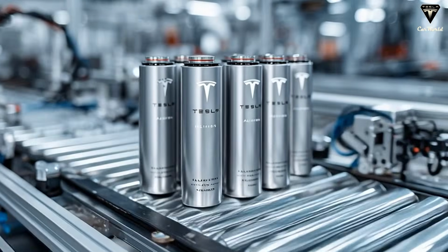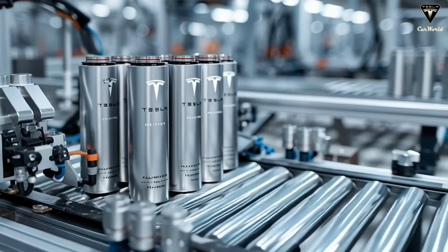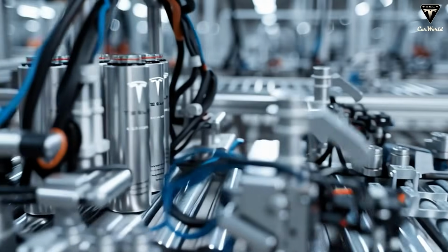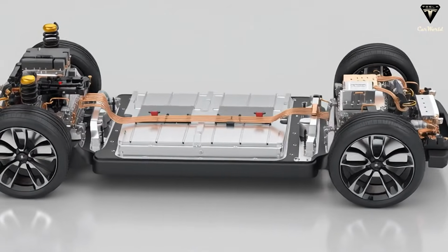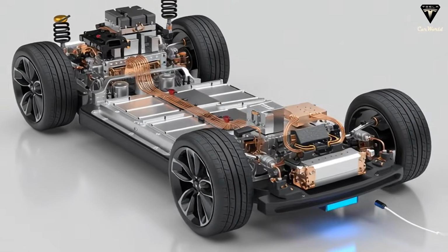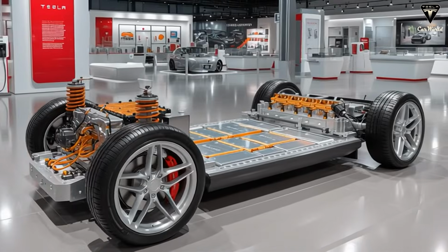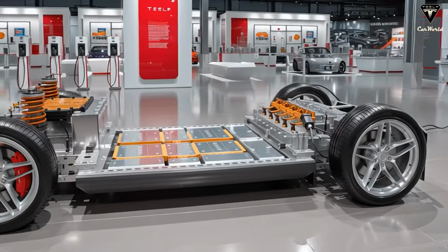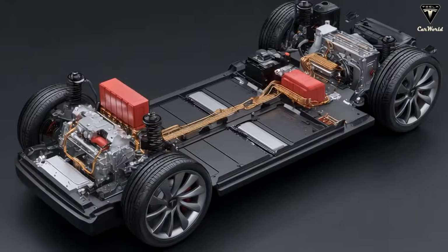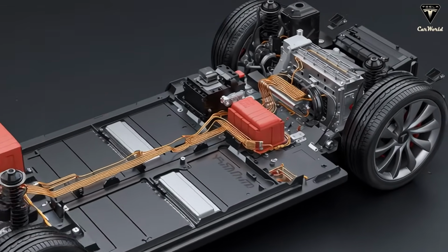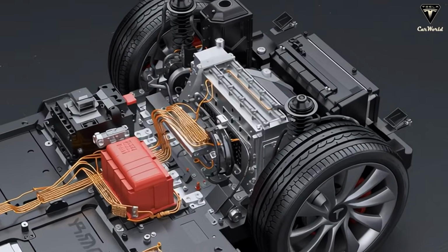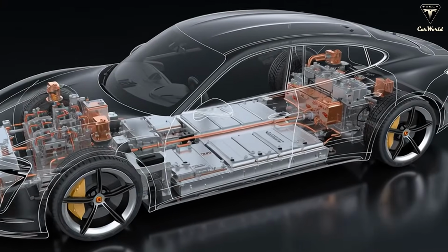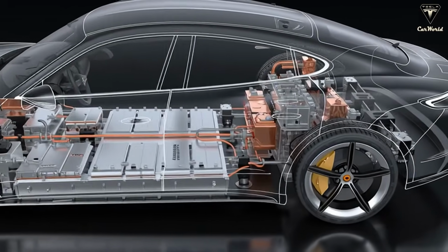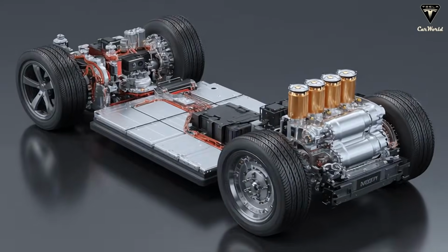After the baseline test, the climate chamber temperature was increased to 80 degrees Celsius and held there for 2 hours. The battery remained inside the chamber during this time to ensure that its internal components fully stabilized at the elevated temperature. Once the cell had reached thermal equilibrium, it was discharged again. And that's when something surprising happened. Instead of losing capacity as most batteries would at higher temperatures, the cell delivered 27.5 amp-hours.